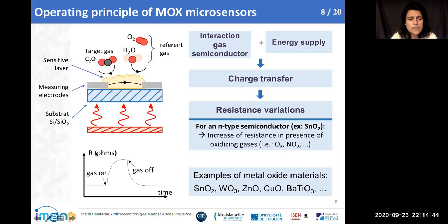So if you look here, the variation of the resistance versus time, if you have an N-type semiconductor like tin oxide and you bring an oxidizing gas at the surface of this semiconductor, you're going to have an increase of the resistance, and when you switch off the gas, you expect to have this decrease of the resistance coming back to the baseline. In my group, we are working on different metal oxide materials like tin oxide, tungsten oxide, zinc oxide, copper oxide, and barium titanate.